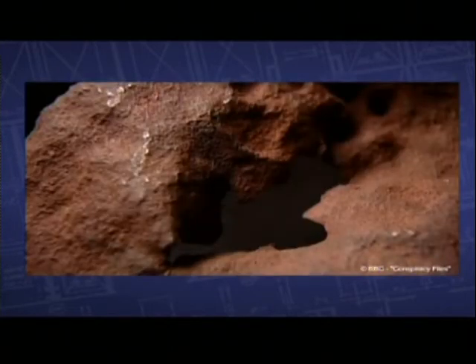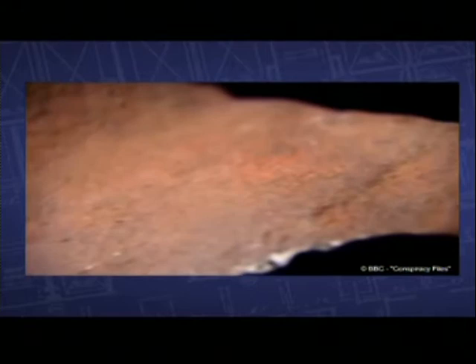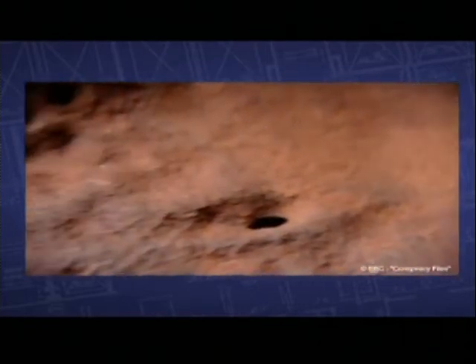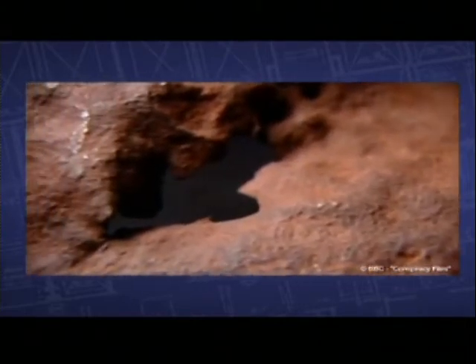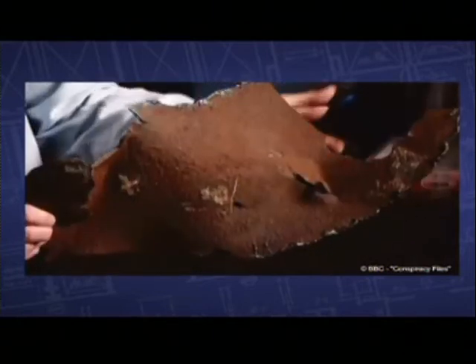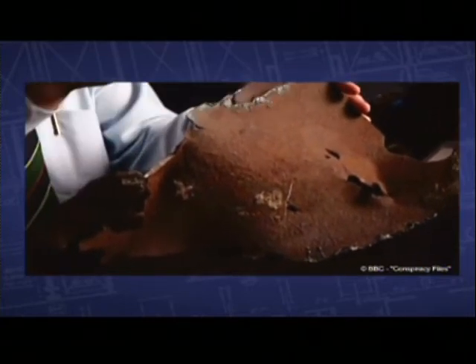It was a surprise to me because it was so eroded and deformed. And so we took it for analysis in the lab. One section of steel was kept. How it got to be in its present state was described by the New York Times as perhaps the deepest mystery uncovered in the investigation. There's parts where the entire half inch of the beam is gone, entirely dissolved right through. And so something happened to cause the steel to really thin and in some places to disappear entirely.